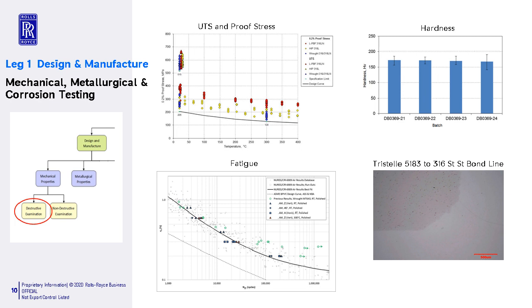In terms of grain sizes, these are a lot smaller than the wrought equivalent, and the grain size is consistent throughout the part. And also from a potential start of life defect aspect, the sizes are very small. This is principally due to the powder particle size that we specify for the metallic powder, and also through the application of the HIP cycle, which we know consolidates porosity, voids, and linear lack of fusion type defects.